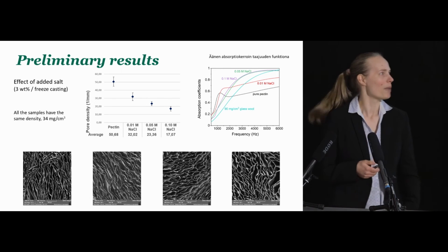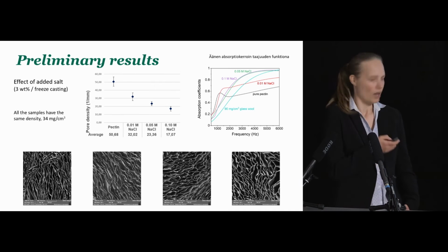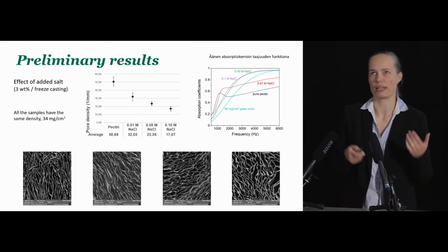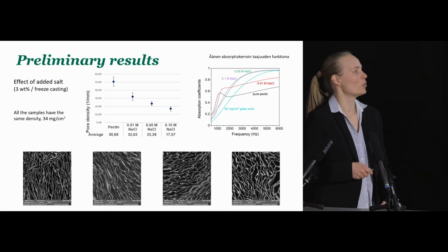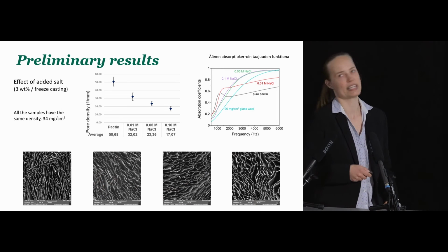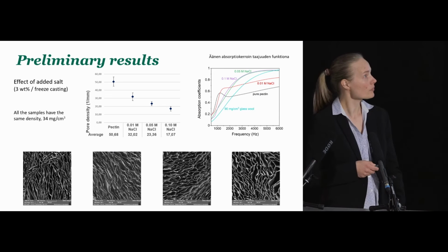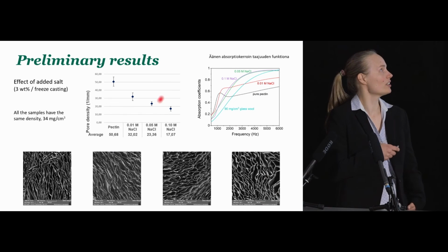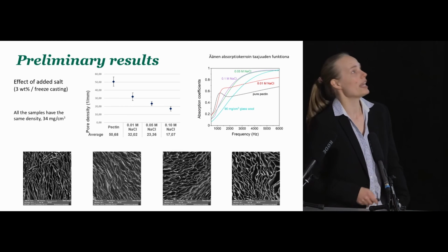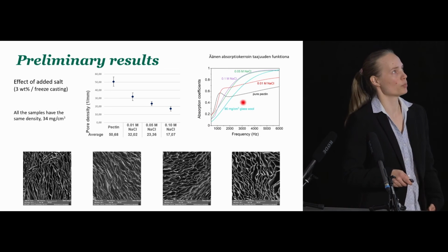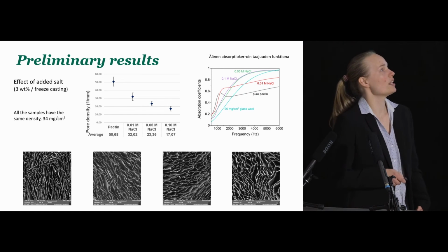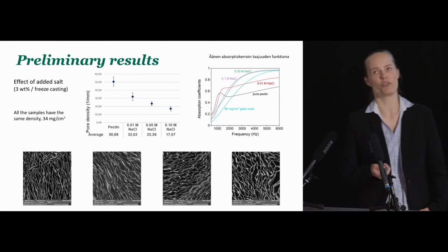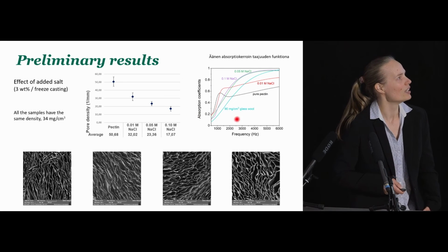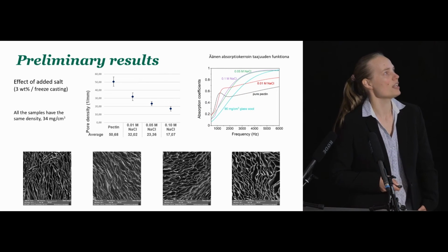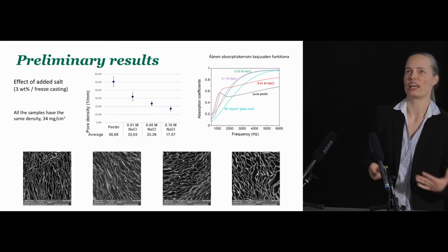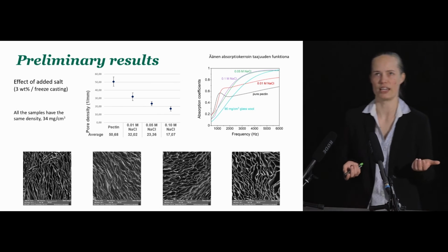And for this task, again, pectin turned out to be quite handy for us. What we found out was that if we cross-link a pectin solution with sodium chloride, we can quite easily tune the pore density of these porous cryogels. And it's nice since we have this continuous decrease of pore density, and that again reflects on their sound absorption properties. With the lowest pore density, we actually had the best sound absorption over the frequency range that we studied. And once again, if you compare it to the turquoise line, which is the glass wool, you can see that with pectin, we actually get better sound absorption over the whole studied frequency range.